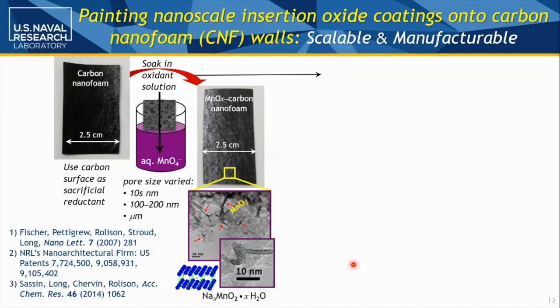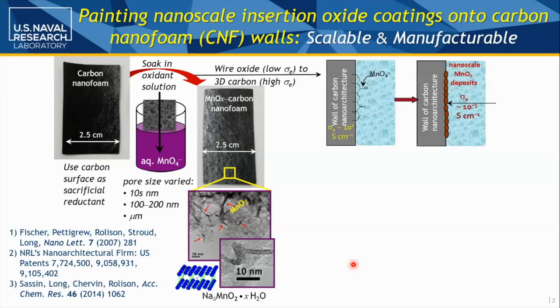And carbon is our starting point for our two terminal devices. So it's got reasonable electronic conductivity. So if you're slathering a poor electron conductor on top of a good electron conductor, yeah, you do have to grind it back up and mix it with carbon. But if you're painting the surface of your good conductor, as we do when we electrolessly deposit the manganese oxide, as the permanganate sacrificially oxidizes that carbon layer, you get nanoscale deposits over your high surface area electrifiable interface. So we take something that's typically on the order of tens to a few hundred Siemens per centimeter conductor. And we're just putting a really thin layer of something that's 6-7 orders of magnitude less electronically conductive. So we don't have a huge ohmic concern in this system.